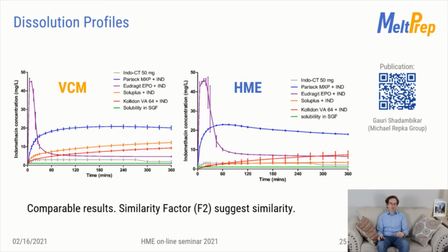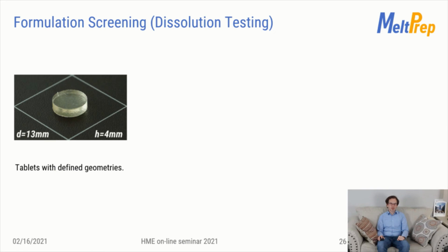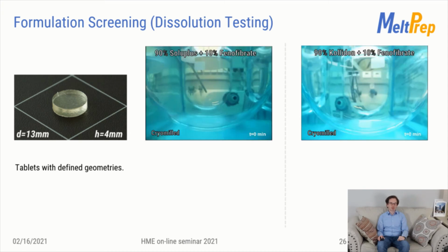The nice thing is you get a defined surface area. You can think about this approach similar to intrinsic dissolution, because you always start off with the same surface area. To illustrate that, we have made an example with 2 different carriers with the same amount of fenofibrate. So we used Soluplus and Kollidon with 10% loading.